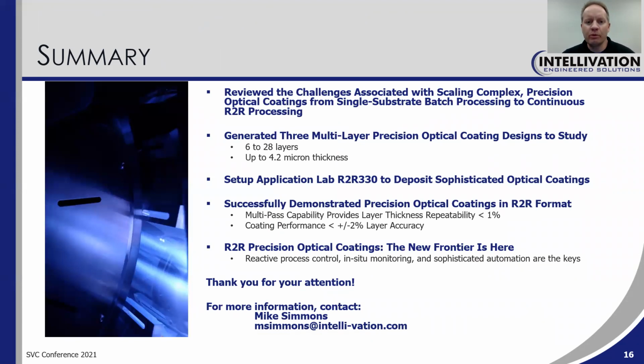So in summary, we reviewed the challenges associated with scaling these complex precision optical coatings from single substrate batch processing to continuous roll-to-roll processing. We generated 3 multi-layer precision optical coating designs to study this, from 6 to 28 layers up to 4.2 micron thickness. We set up the application lab R2R 330 tool to deposit these coatings, and we successfully demonstrated these coatings in roll-to-roll format, utilizing both multipass capability and great accuracy for each layer.